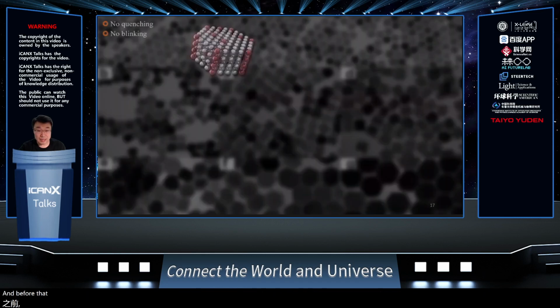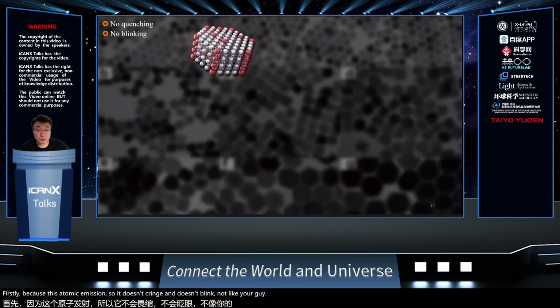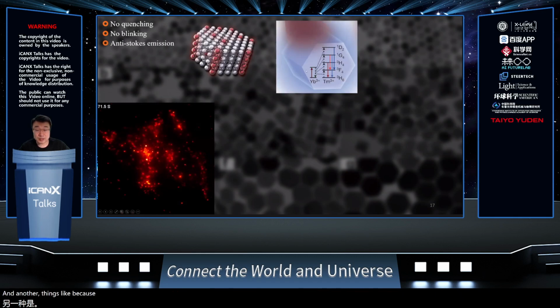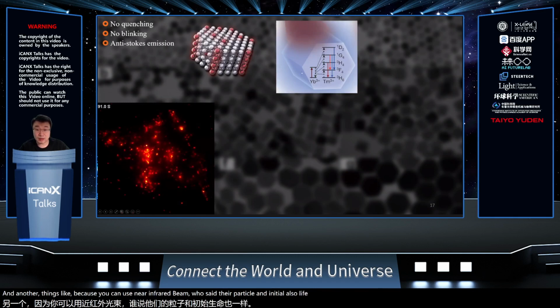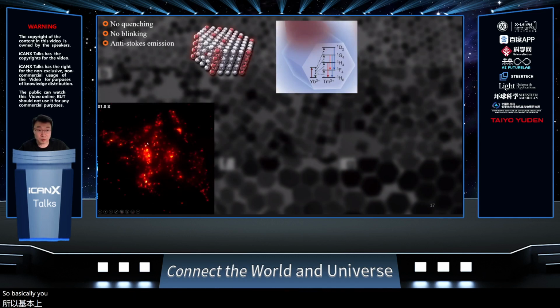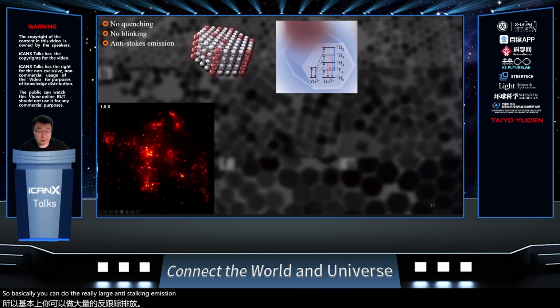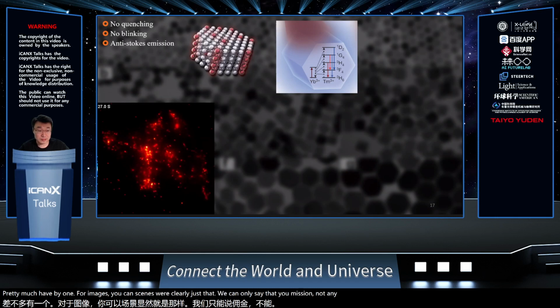Before that, I want to mention the benefits of this nanoprobe compared with others. Firstly, because this is atomic emission, it doesn't quench and it doesn't blink, not like your dye. So you can run a fluorescence experiment for even one day or several days. Another thing is that you can use a near infrared beam to excite your particle, and the emission is quite far away from the excitation. So you can get a really large anti-Stokes shift, and you pretty much have background-free imaging. You can see clearly that we only see the emission, without any autofluorescence.